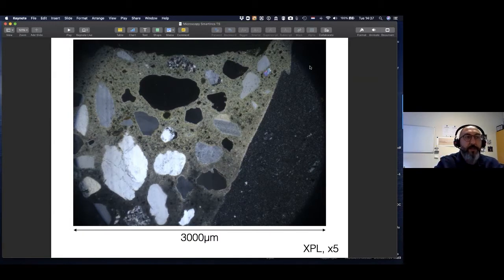You see it's 3 millimeters. You're looking at the surface of a piece of concrete, and you see it is quite bright, coming all the way down to a certain level, and after that it's all dark. Can anybody tell me why this is the situation here? What's going on here? Why do I have a cement paste here, the binder, super bright, down to a certain level, and then it's going quite dark? Anybody in 1, 2, 3 seconds?